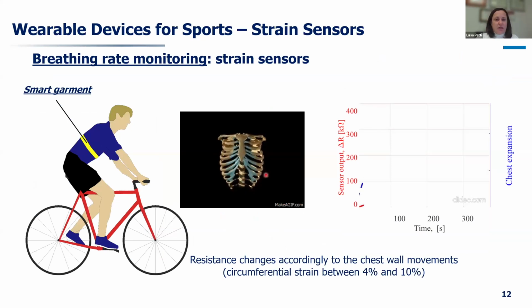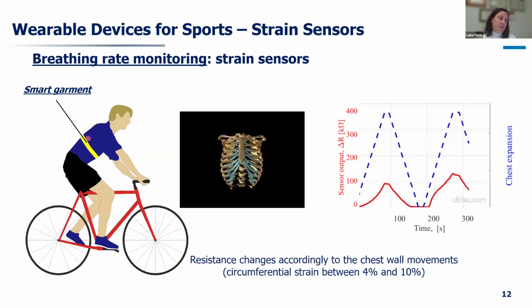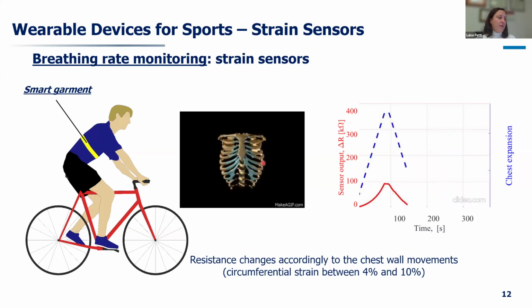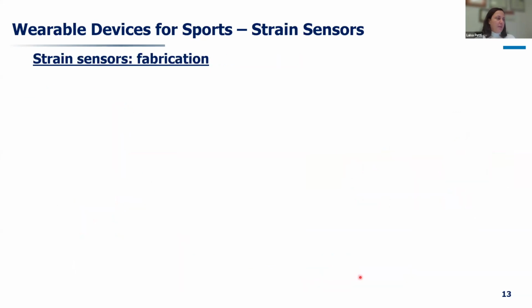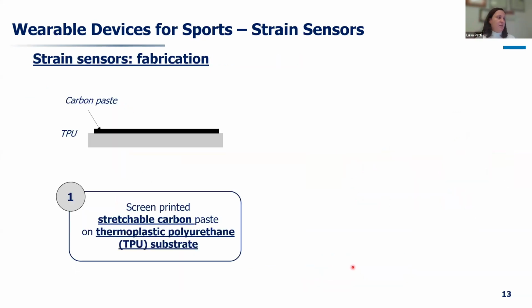and we looked into an extremely easy sensor technology, basically strain gauges, so resistive sensors placed close to the chest in order to be able to detect the chest movements, which basically account for a circumferential strain between 4 and 10%. And we did this using completely printed devices. Basically not printing on textile, so we didn't choose to print directly on textile, but we decided, in this case, Martina was the researcher responsible in the project for all the experimentation. We decided to work directly on TPU with a carbon paste, which was screen printed, so the same technology used for printing of the logos of our t-shirts.